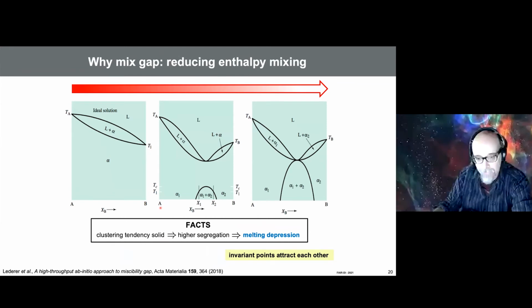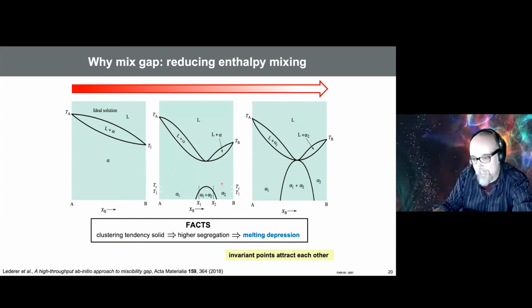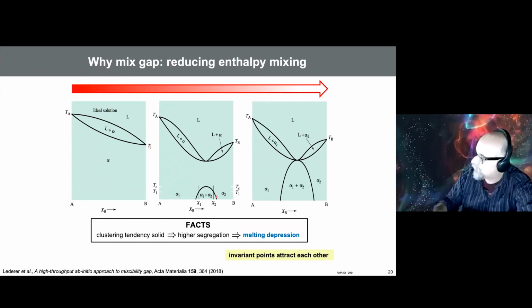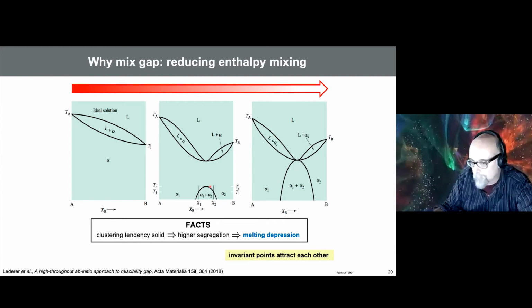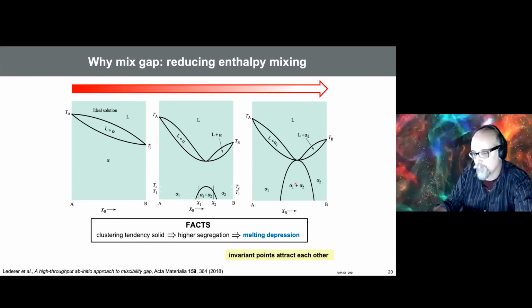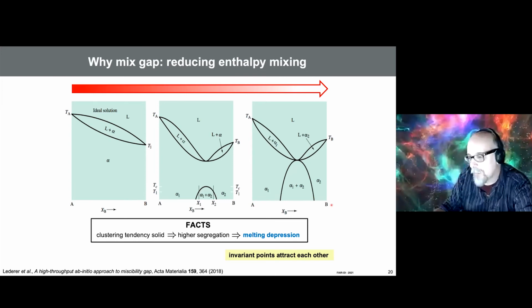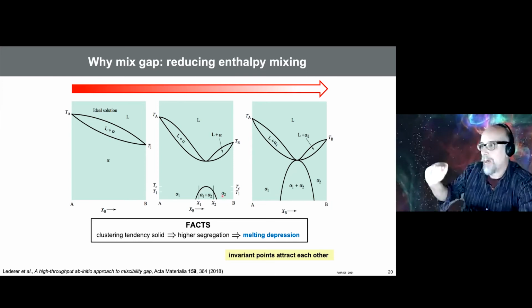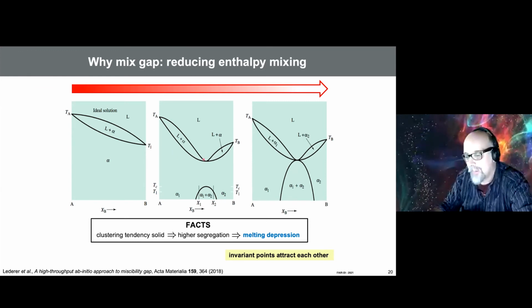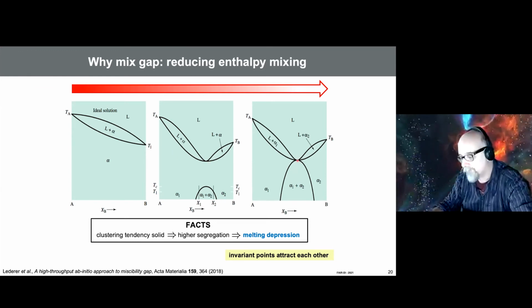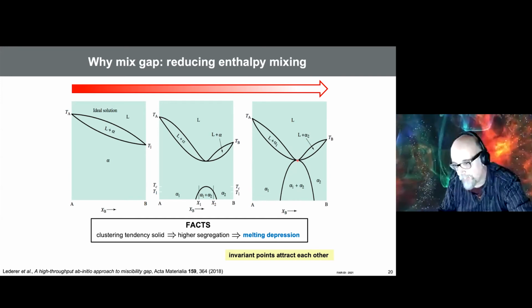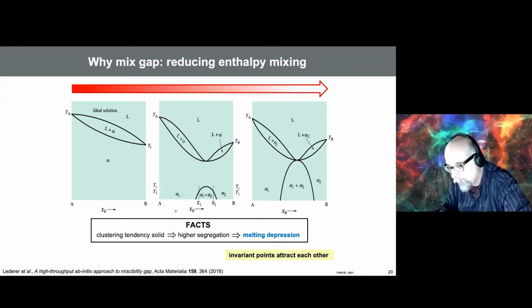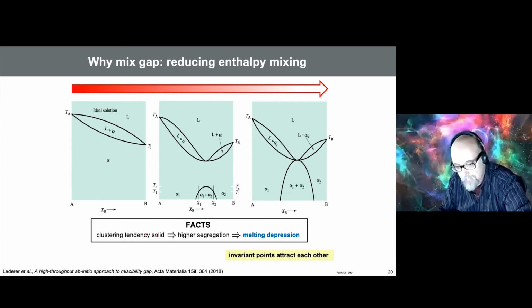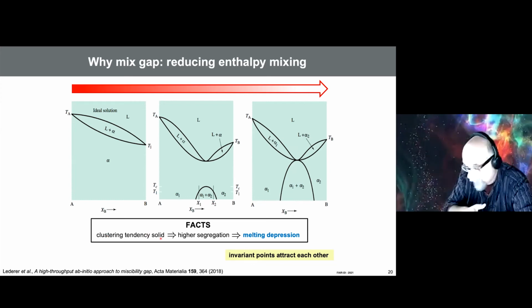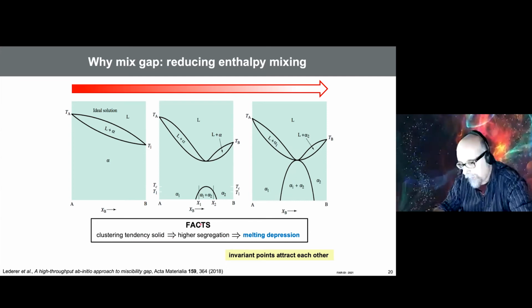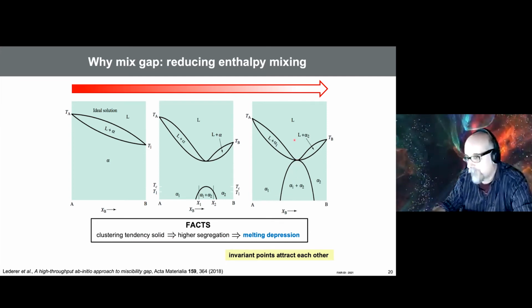Duke versus UNC, right? A likes more A, B likes more B. So at low temperature, there is this kind of segregation. So you need to increase the temperature to start mixing them. Okay, you see where you have solid solution. So if the hate between A and B increases, then these miscibility gaps go up until they touch the congruent melting here, and it forms the eutectic or eutectoid phase diagrams. Okay, so this was already known for a couple hundred years. So the clustering tendency of the solid, given by the hate between A and B, creates a high segregation, and therefore melting depression in the liquid.